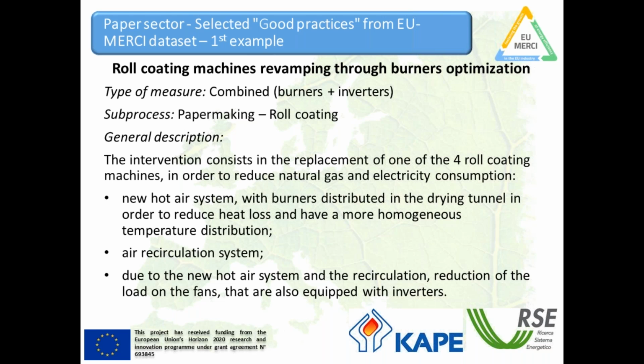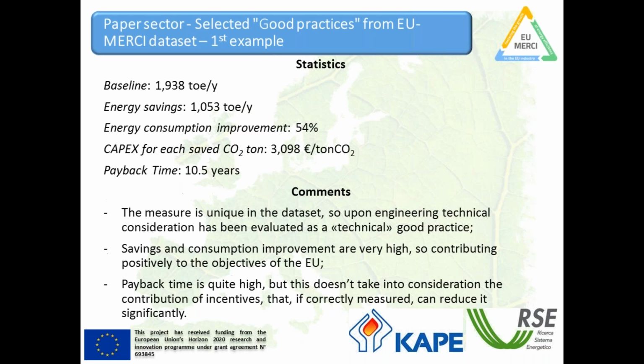The sub-process is paper making, roll coating, and the intervention is described by the general description, but basically is a new hot air system with a different distribution of the burners in the tunnel that can give a more homogeneous heating, so a temperature distribution that is more homogeneous and less fuel consumption. Of course, related to the hot air system, there is the air recirculation system, and the second action in this measure is the reduction of load on the fans thanks to the new air recirculation system, but also to the use of inverters on the recirculation air fans.